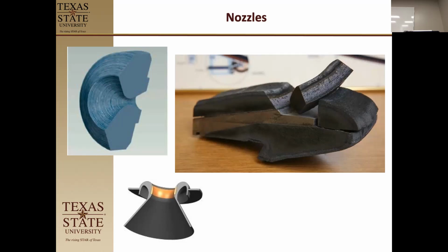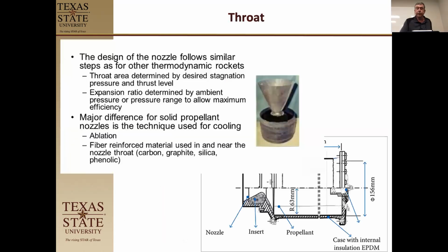The size of this cone is directed by how much thrust and force you're getting. You need to have it not too big and not too small to get maximum thrust. The idea is that by the time you get out to this edge, you've had all of your thrust prepared and the pressure differential is almost zero here. So you actually want this pressure balance to happen. But that's why this place right here is where the highest heat, the highest pressure, and the highest concentration of particles exists. And that's where the ablative materials are actually used.